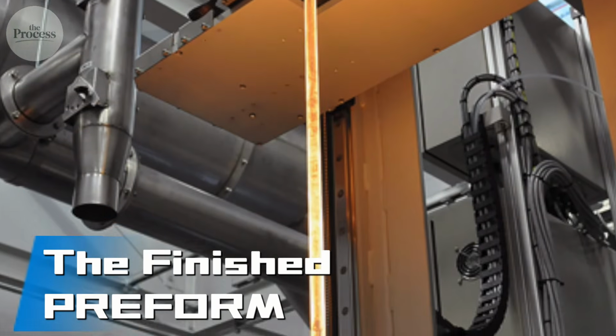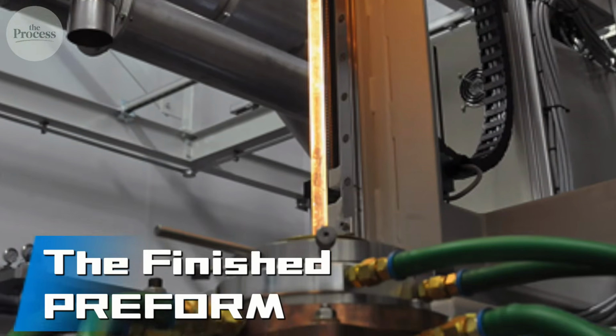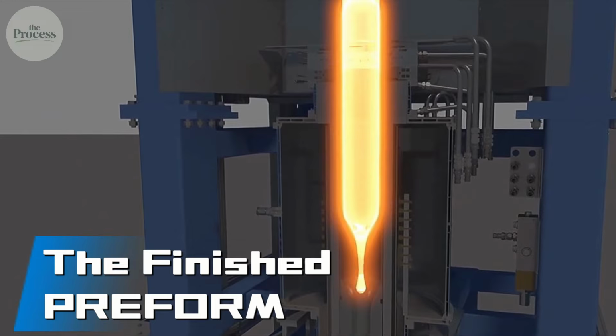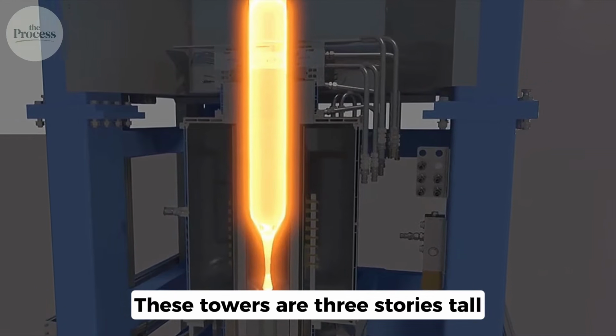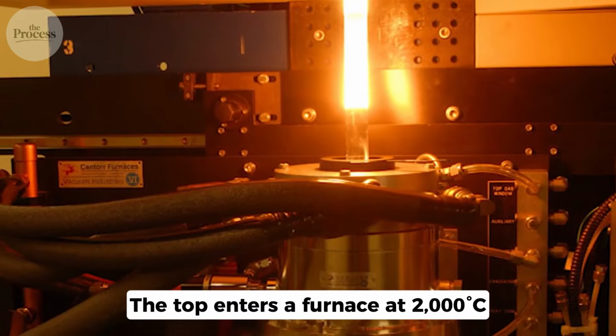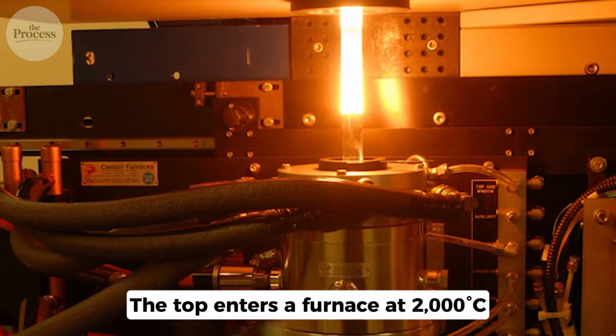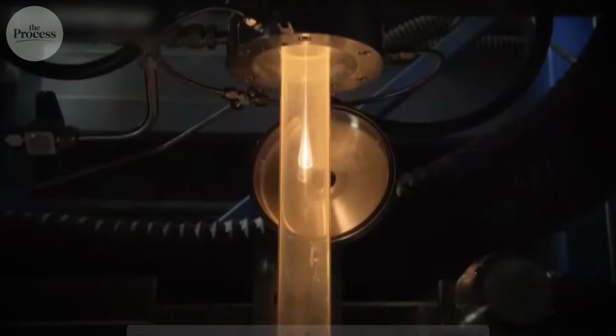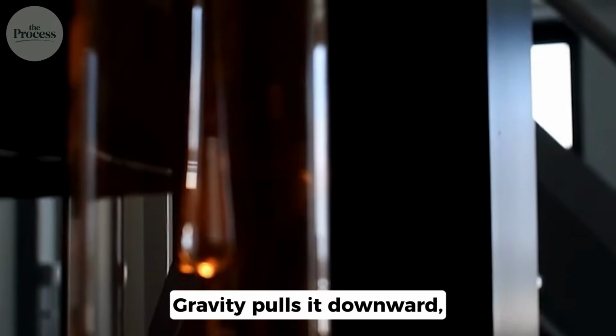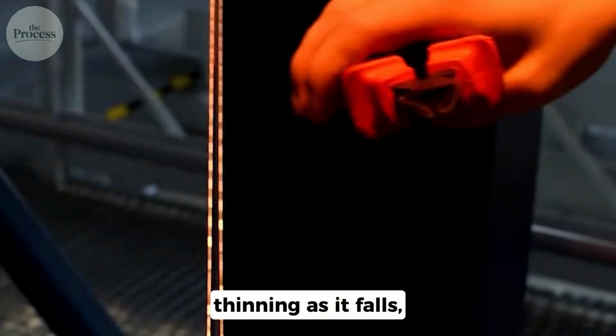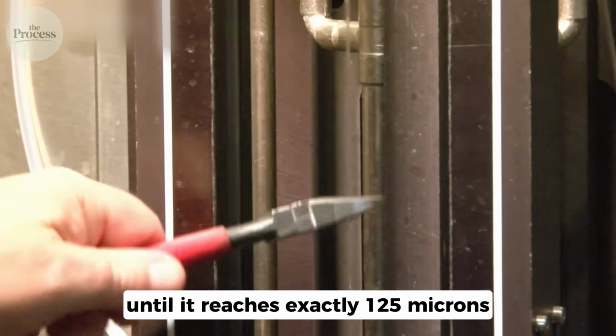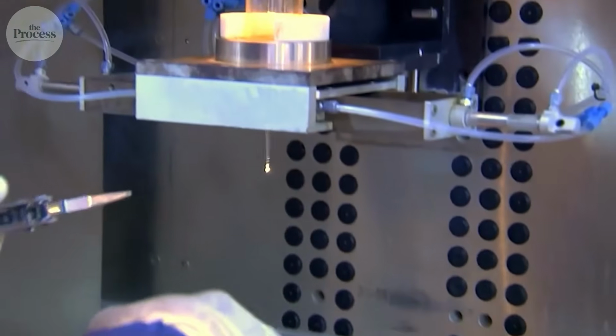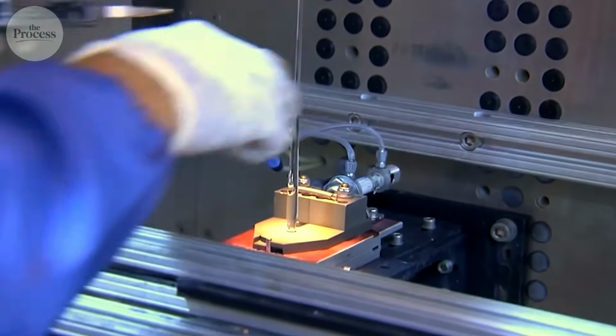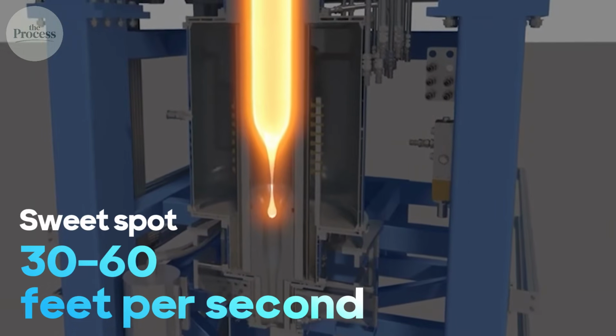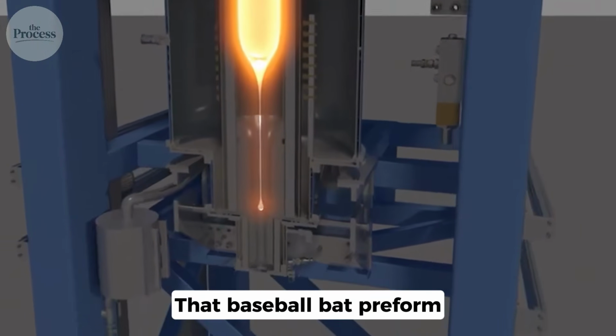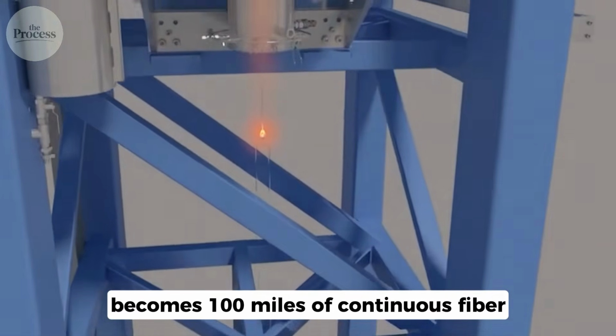The finished preform, perfectly pure, perfectly layered, about 10 inches in diameter, gets loaded into a draw tower. These towers are 3 stories tall because gravity needs distance. The top enters a furnace at 2,000 degrees Celsius, hot enough that glass flows like honey. We don't push it, don't squeeze it. Gravity pulls it downward, thinning as it falls until it reaches exactly 125 microns. Speed matters. Too fast breaks the fiber. Too slow creates imperfections. Sweet spot is 30 to 60 feet per second. That baseball bat preform becomes 100 miles of continuous fiber.